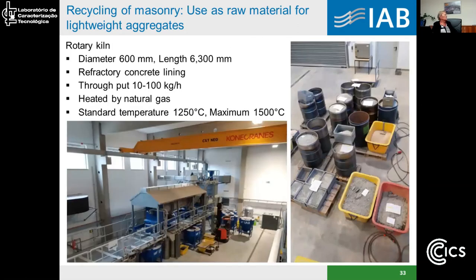Okay. Here you see a rotary kiln that we have available for nearly 2 years at the institute. It has a diameter of 600 millimeter, a length of 6,300 millimeters, and refractory concrete lining, a throughput of between 10 and 100 kilogram per hour. It is heated with natural gas. The standard temperature is 1250. Maybe we can also achieve a maximum temperature of 1500, but that's not so good for the lining.